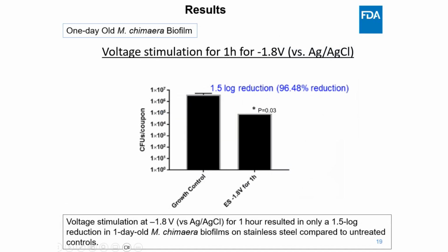So let's take a look at our initial results, starting with the early stage NTM biofilms, which are 1 day old Mycobacterium chimaera biofilms. Based on the previously published literature, we began our testing by using minus 1.8 volts versus reference electrode, a cathodic voltage that has shown effectiveness against Staphylococcus aureus biofilm. So we wanted to use the same voltage stimulation in our NTM studies to see what kind of effect we would see on the biofilm viability.